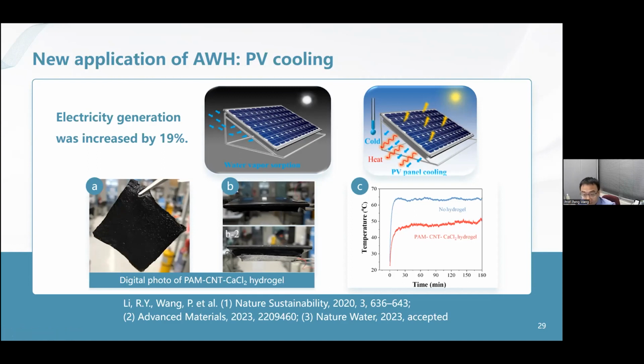Now, water evaporation is a phase change process that takes a lot of heat. It's like our human body sweating, which is how we keep our body temperature stable. In our case, we use the hydrogel sweating to reduce the temperature of the PV panel. With this design, we reduce the temperature of the PV panel, and therefore we were able in our test to increase the electricity production rate by 19%. This is a very significant energy enhancement.